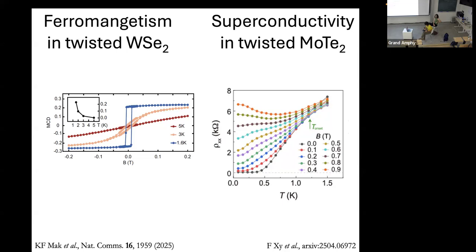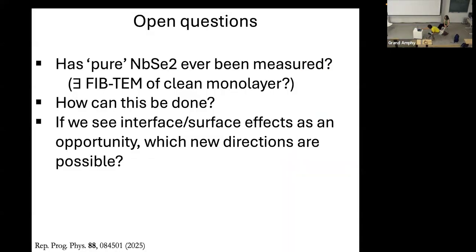Yeah, okay. But I want to zoom out to the theme of the discussion that Karis raised: once you move to the monolayer regime of any material, especially a superconductor, you're extremely sensitive to the materials which interface it, whether from below or from above. Also referring to the comments made by Miguel, MBE really depends on the substrate, right? Because you grow on a substrate. Yeah, that's true. That's why, for example, we measured the critical temperature of NbSe2 at monolayer on four different substrates. Bilayer graphene, silicon carbide, and we thought, okay, but at the end, this is a metal, so maybe it's affected. But we grew it on a monolayer boron nitride, and we measured the same critical temperature. If it's a metal, so it's all around 3 K or something. Yes, something like that.